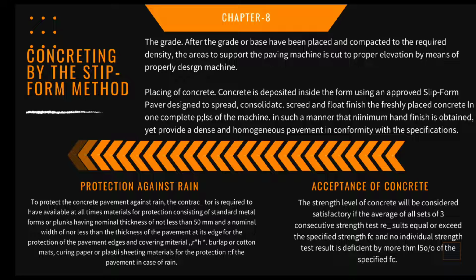The strength level of concrete will be considered satisfactory if the average of all sets of 3 consecutive strength test results equal or exceed the specified strength f'c and no individual strength test result is deficient by more than 15% of the specified f'c.